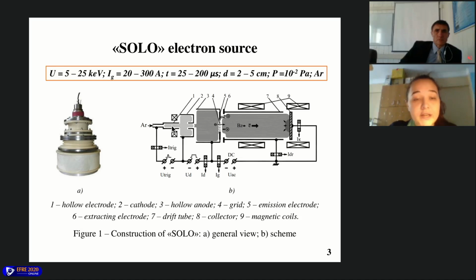So the initiating discharge is ignited between the hollow electrode and the cathode. The main arc discharge is burning between the cathode and the hollow anode. The accelerating voltage is applied between the emission electrode and the extracting electrode. Electrons from the beam are transported to the collector through the drift tube in the magnetic field of two magnetic coils.